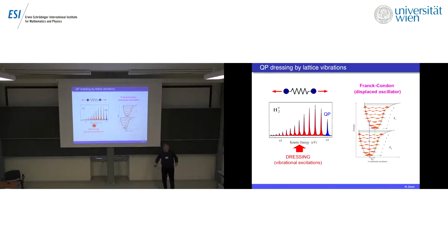All right, so in particular, here we're interested about phonons. So the simplest system you can think of is a molecule, a diatomic molecule, H2. And if one does a photoemission on H2, this is what one observes. So this peak here would be the quasi-particle peak, so to speak, and then you have a progression of vibrational and rotational states that are hidden here, corresponding to the fact that when we excite the system and we remove an electron, we can leave it either in its ground state or in the ground state plus 1 quantum of vibration, 2 quanta of vibration, and so on and so forth. So all this dressing can be directly measured by photoemission. And essentially, it's the Franck-Condon idea of